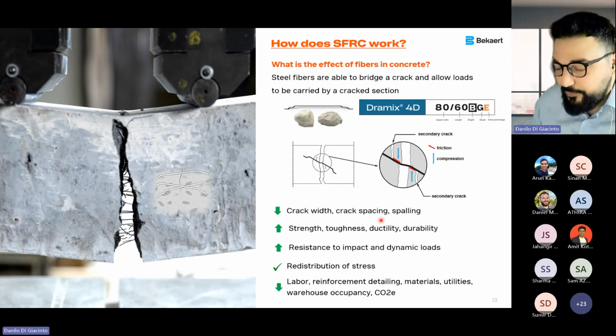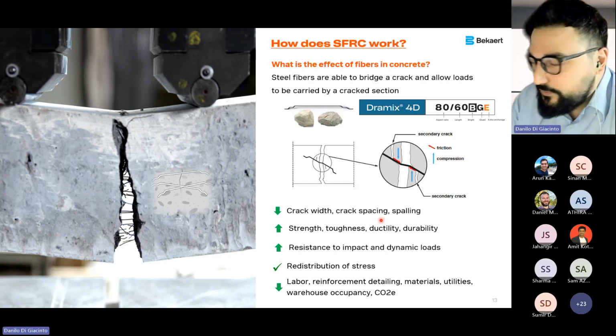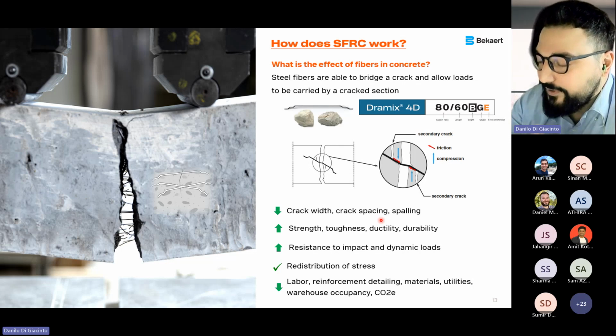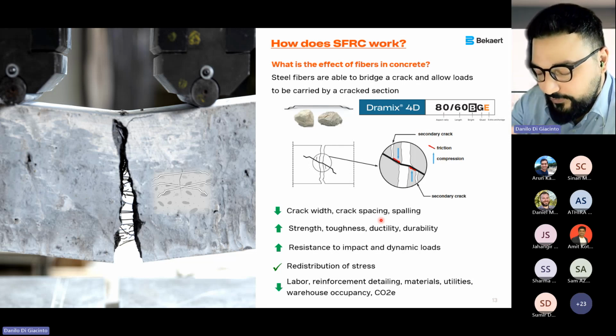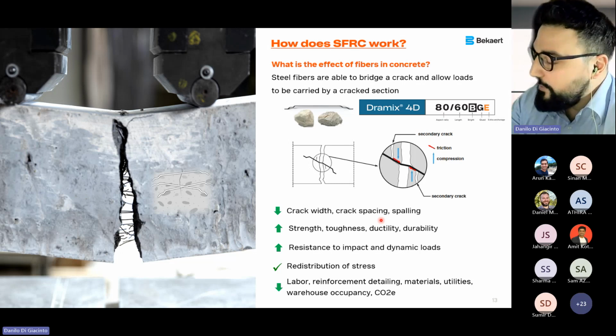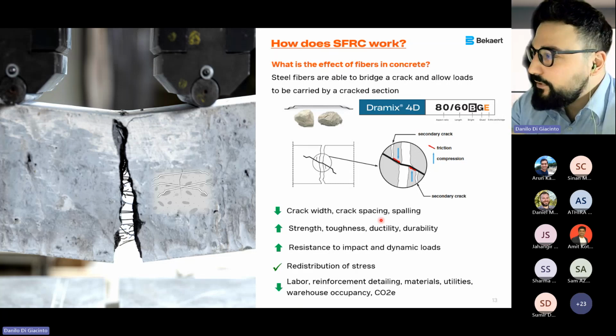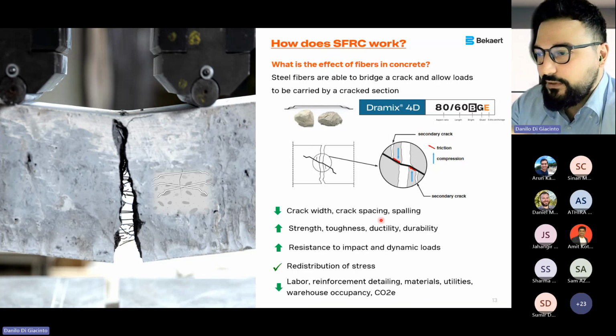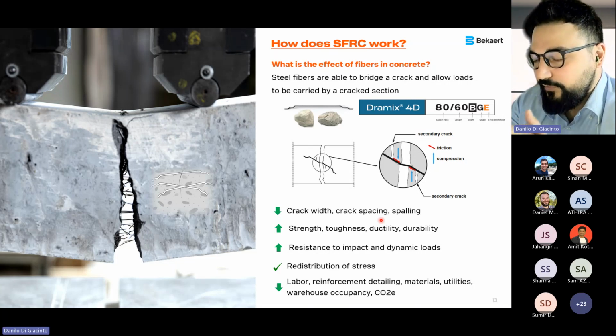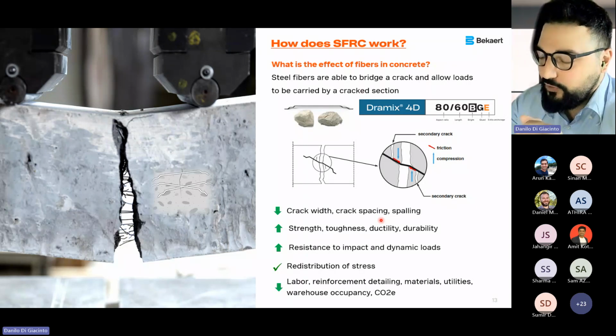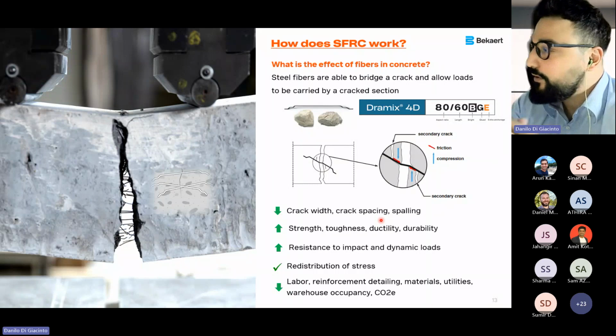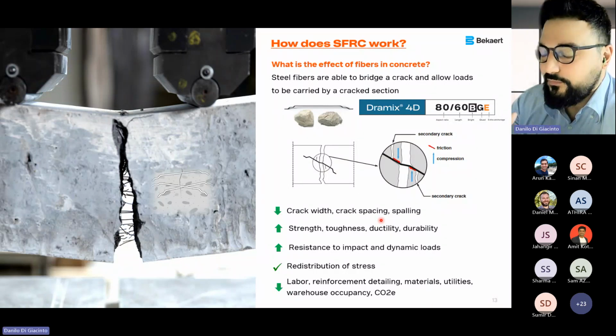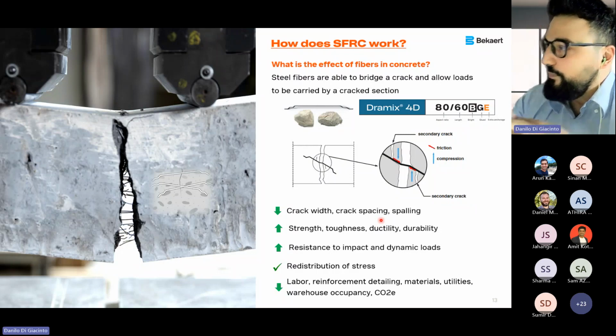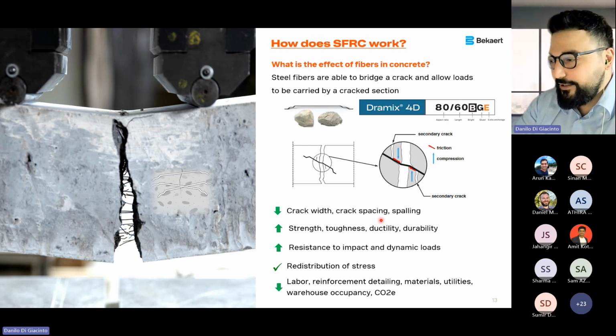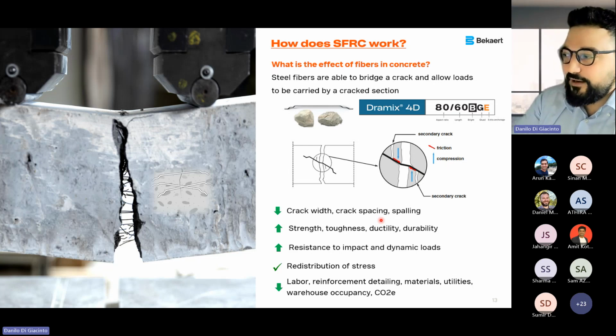How does SFRC work? This is a very important concept. When you add fibers to your concrete, you have a new material, a composite material, a concept which is totally different from the standard reinforced solution. You have reinforcement everywhere, and as soon as a crack appears, the steel fiber can bridge it. The cracking can be more distributed. You have thinner cracks. You have the spacing between the cracks, which is smaller. And thanks to this feature, so because we can achieve the bridging of cracks in the early stage, we can improve the strength, the toughness, the ductility of the concrete, and obviously also the durability.